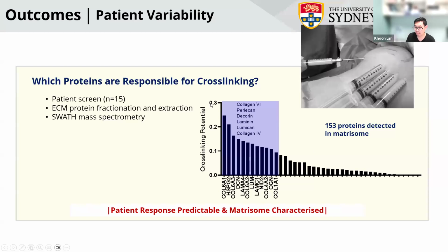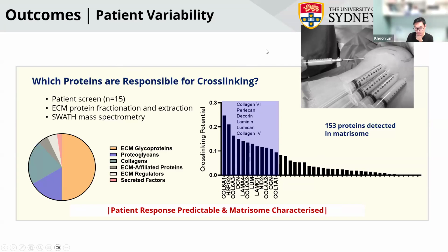So we did LCMS in this case to look at protein fractionation. We extracted them, we looked at composition, and we found that a lot of the top hits of the proteins that are detected in the matrisome are proteins that have tyrosine. So you have collagen, laminin, collagen 6 and 4, for example, and all of these are rich in tyrosine. And that is really important for us.